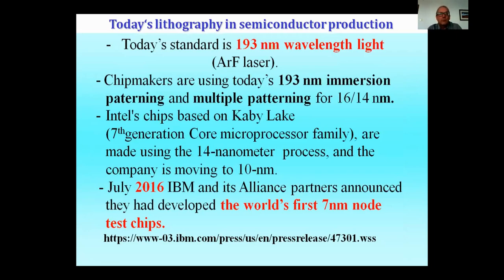So we can say that today standard lithography in production is with excimer laser with wavelength 193 nanometers. And the chip makers are using this lithography with immersion patterning and multiple patterning.